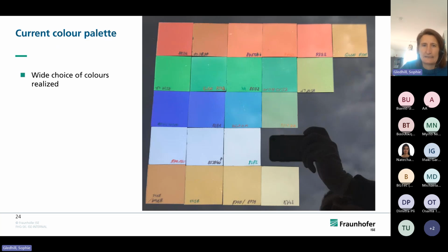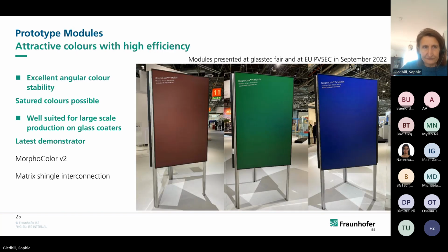And we have a wide color palette. Basically, you can design whichever color you want. And we retain our high efficiencies. So we have excellent angular color stability. I'm showing on the graph the modules that we presented a year ago at the EU PVSEC in 2022. They're well suited for large-scale production on glass coaters. And absolutely, the rich color is achieved because we use the Fraunhofer matrix shingle interconnection, so we don't have any front contacts in this particular technology. Without the color coating, you have a very black cell, and with the color coating, you have a very homogeneous color.